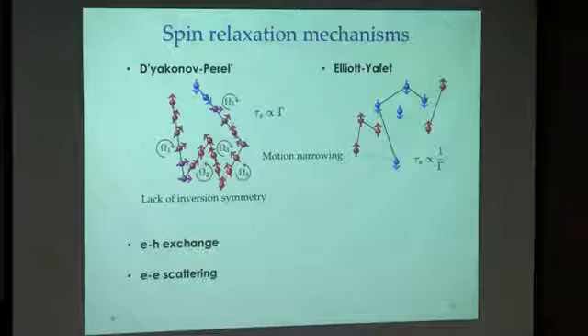So let me discuss a little bit about the spin relaxation mechanism here. Because of the lack of inversion symmetry, it's possible to have both the Dyakonov-Perel and the Elliott-Yafet mechanisms. The way the Dyakonov-Perel mechanism works is that a spin precesses about an effective magnetic field resulting from spin-orbit coupling between each collision. That effective field changes between collisions, and you have motional narrowing. So the spin lifetime is actually proportional to the momentum scattering rate. But in the Elliott-Yafet mechanism, the spin relaxation is inversely proportional to the momentum scattering.